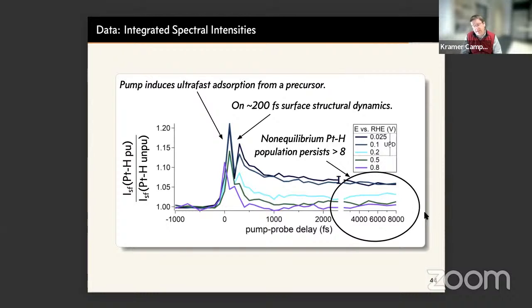It is clear, though, that if you look at somewhat longer times, so this is delay in femtoseconds, and this is now a few picosecond delay, there is a kind of offset here, which only occurs within the UPD region. So now, if you are within the UPD region, you have a rapid increase, which seems to persist to somewhat longer timescales. It becomes more apparent as you get into the UPD region at, say, a few hundred femtosecond timescales, it's clear there is a large dip, and presumably this is related somehow to structural dynamics. So this is interesting, right? This tells us something perhaps about what's going on.